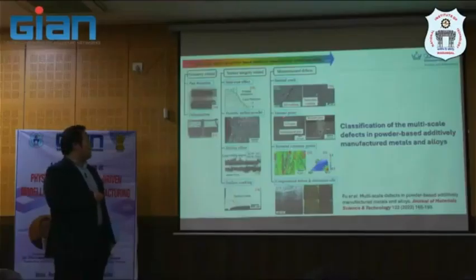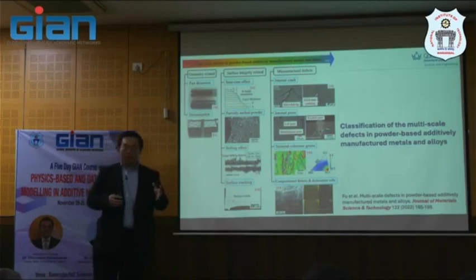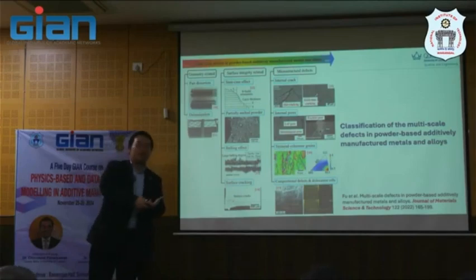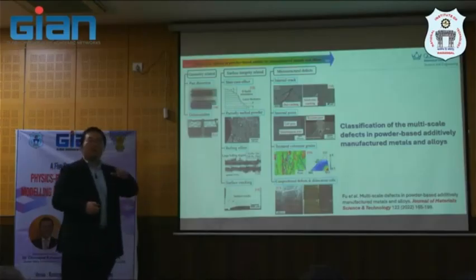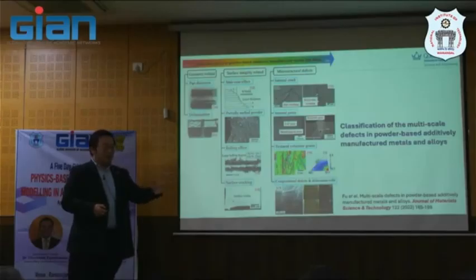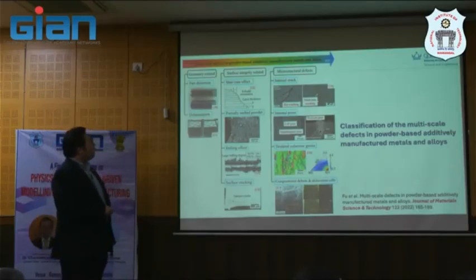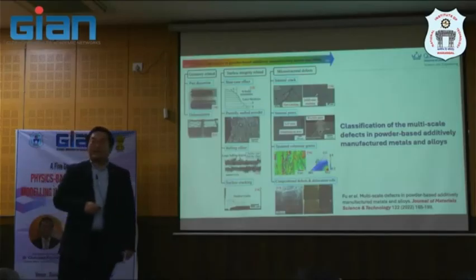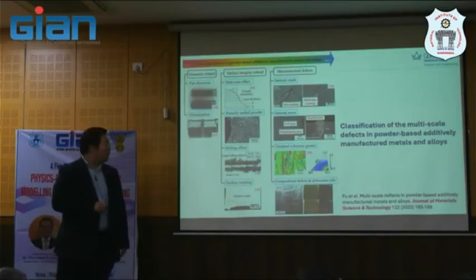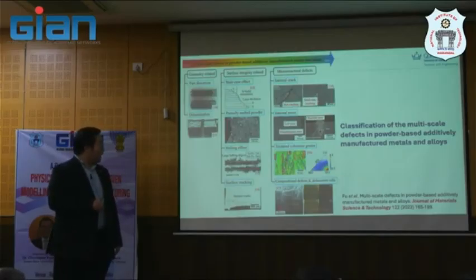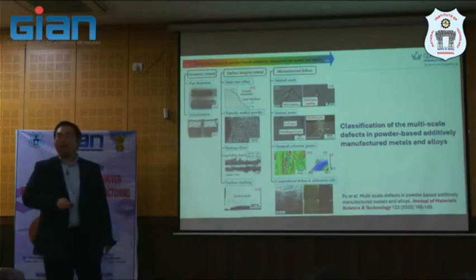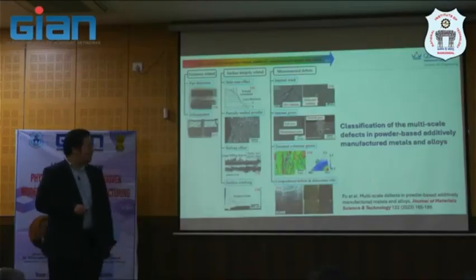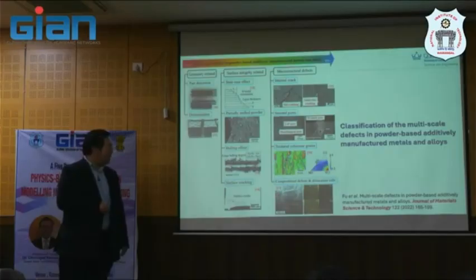here as a microstructure defect, and I mean porosity is also classified in a number of ways. You may know lack of fusion, voids, process-induced porosity, and also pores trapped during the powder production, something like that. And the texture and columnar grains, I mean, they define columnar grains as defects, or the textured material is not preferred in the process. And also, last but not least, this is something I will give an example of in the next lecture, which is a compositional defect. And then this location defect that we actually call cellular structure in additive manufacturing.